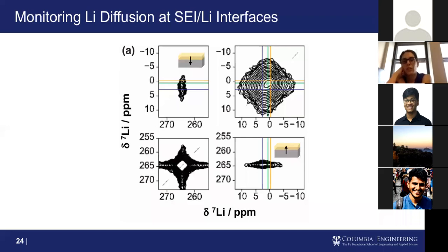And you can run it in such a way that you see exchange between things in the SEI. And that's what this big blob here is showing. So I'll walk you through this. This blob here is showing lithium metal. So this shows up around 265. This diagonal shows just a simple NMR spectrum where we see our SEI that I just showed you on the previous slide, and we can assign the same color coordination where we have our lithium fluoride, our organic lithium species, and our lithium oxide. And then we have our lithium metal further downstream.